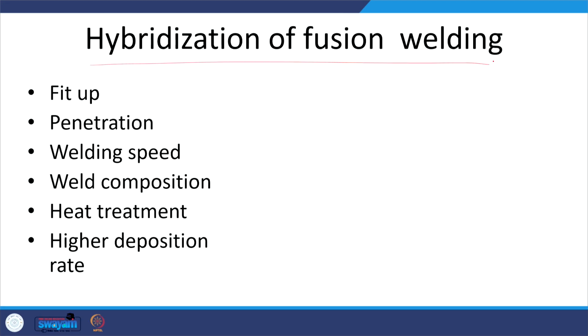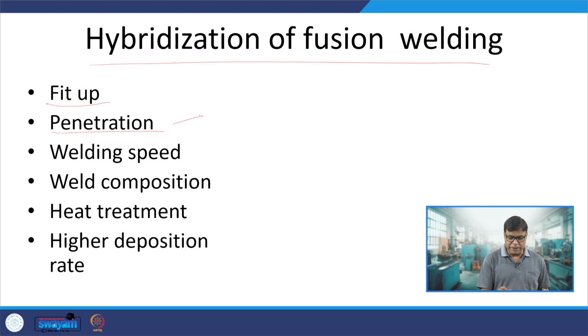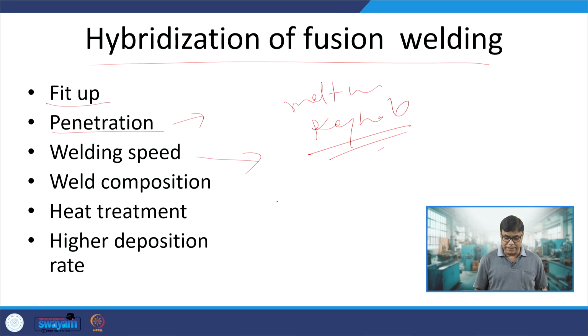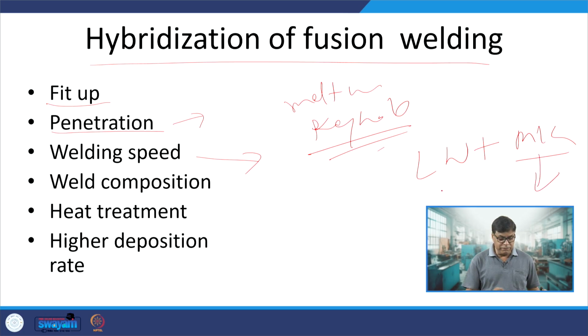So, the hybridization of fusion welding processes helps in reducing the fit up requirement. It helps in increasing the penetration, because one may be working in melt-in mode, another may be working in keyhole mode. Keyhole mode allows the deeper penetration. When both work together, our welding speed is enhanced. It is also possible to club laser welding with MIG welding. So, MIG will help in applying the filler metal of the desired composition to adjust the weld metal composition as per the need, while realizing the deeper penetration and a faster welding speed. Okay. When the heat sources are used sequentially, then PWHT of the weld zone can be realized, and higher deposition can also be realized when the hybridization of the fusion welding processes is done.